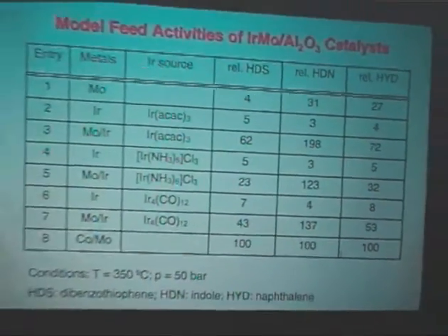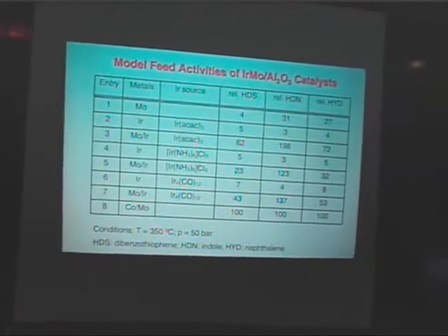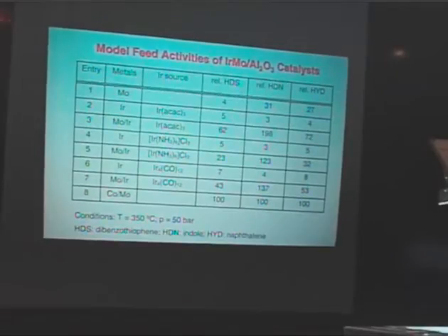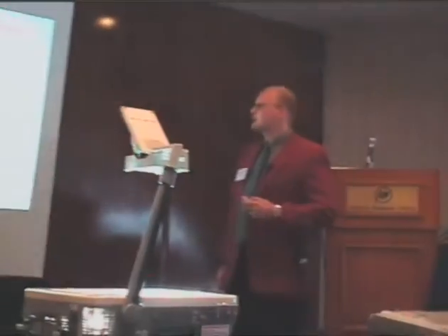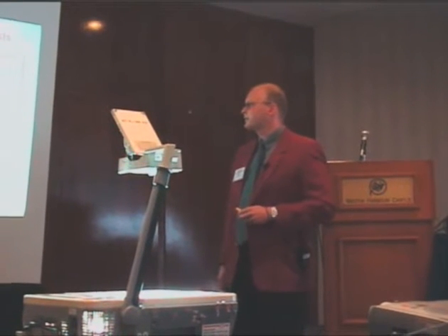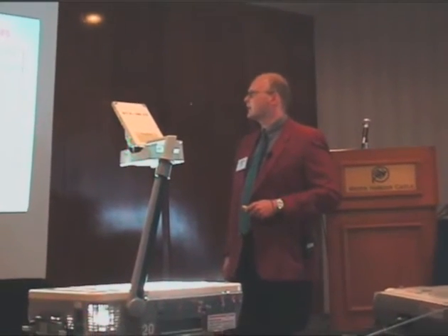The pure iridium catalysts show generally a very low activity in all experiments, for HDS, for HDN, and for hydrogenation. This is independent from which iridium source the catalysts were prepared. The bimetallic systems show a moderate activity